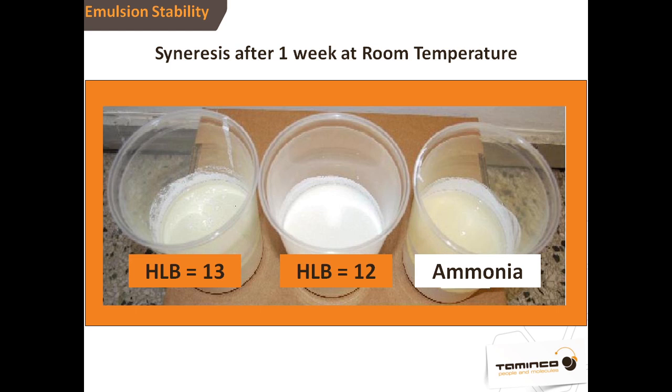Now for other molecules, you can develop alternative calculations of the HLB. The only thing that's really important is that the calculation be applied consistently across that entire class of molecules. What we adopted was a calculation very similar to the one used for fatty alcohol ethoxylates. We take the alkoxylated portion of the alkanolamine and divide that molecular weight by the total molecular weight of the alkanolamine, and then multiply by 20.